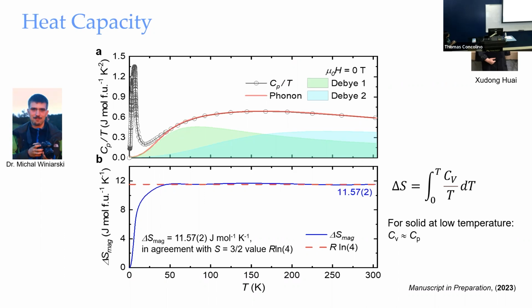And if you see the color green here. And the ΔS mag can be extracted by taking this integral. And we're approaching about 100%. So we recover 100% entropy across the phase transition for this material, indicating that it undergoes a long range magnetic ordering.